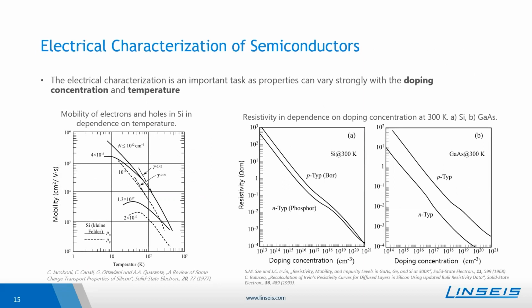Then, as a second example of why the characterization, here the electrical characterization, is an important task. The electrical properties also depend strongly on the doping concentration and on the temperature. Here is an example of the mobility of electrons and holes in silicon and its dependence on temperature. So here's the mobility, here's the temperature, and one can clearly see that the mobility changes with temperature and also for different concentrations.